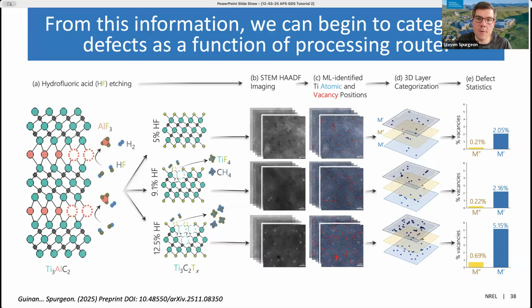So where this plays a role then in understanding the synthesis of the MXenes is that we can look at the effect of different etching routes on parent MXene and on parent MAX phases and how that affects the MXene that is formed. We can take a variety of different images of the material that represent all the variability or a good portion of the variability within the MXene. We use these machine learning approaches to classify the atomic and vacancy positions. And then we can take that a step further and actually classify where are the defects within the MXene lattice, how do those distributions change, how do those defects cluster, and come up with an incredibly sophisticated nomenclature to describe point defects within the MXenes.